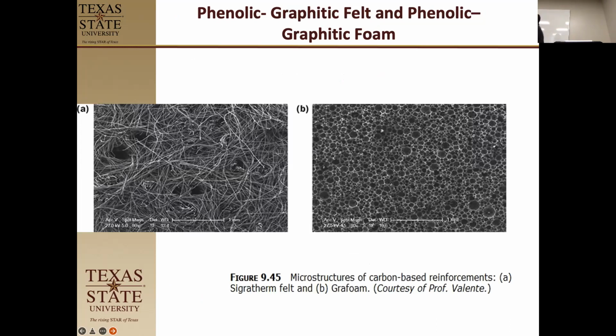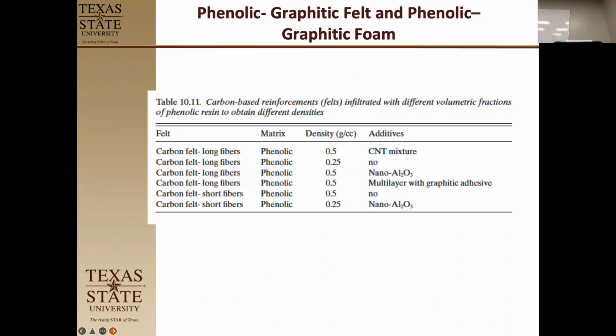Okay, so this is a different one. This is a different one looking at a phenolic, but then they're starting with a graphitic felt. So basically, you can pyrolyze this graphitic felt, or you're starting with a graphite-based foam. And then they're going to fill these and look at their different thermal transfer, different ablation properties. Okay, and on this one, there are different little things where they're going to do carbon felt with long fibers, carbon felt with short fibers, phenolic resin, and then they're looking at adding carbon nanotubes, nothing, nano alumina, multi-layered graphitic adhesive. So it's basically clumps of graphite. So it's graphene that haven't been separated. Nothing with short fibers, and then nano alumina. And they're going to look at their different properties here. So nano alumina is competing against carbon nanotubes and graphite particles.